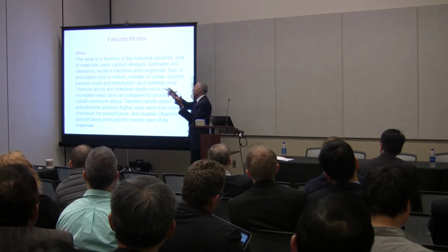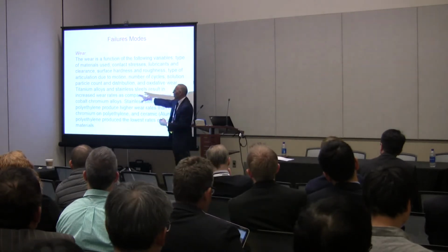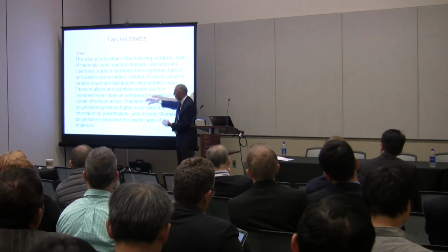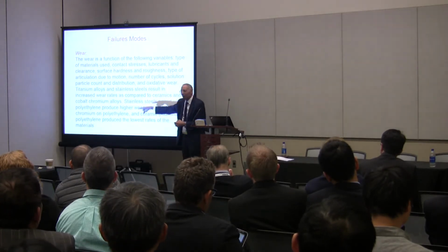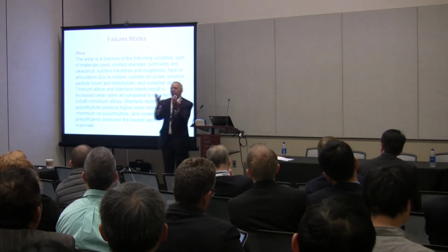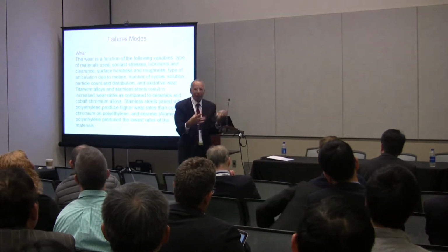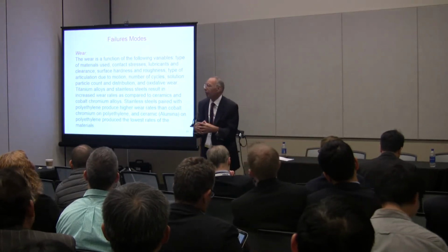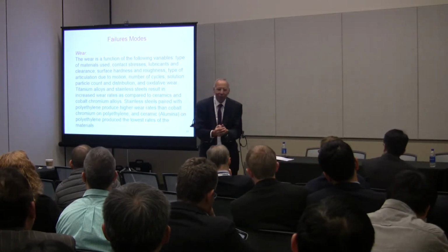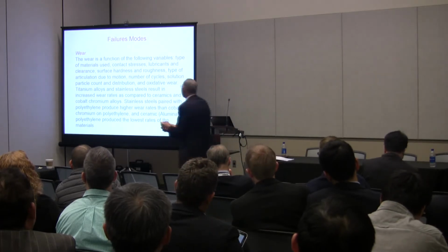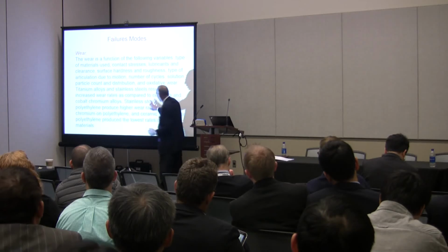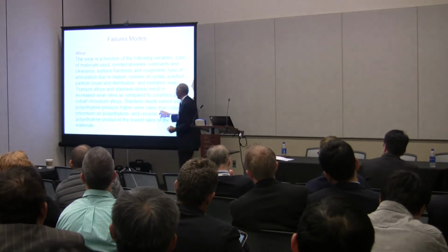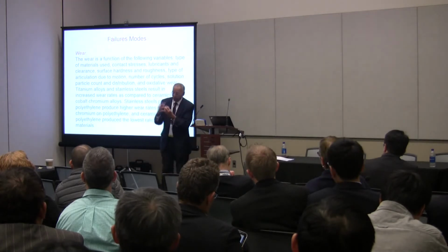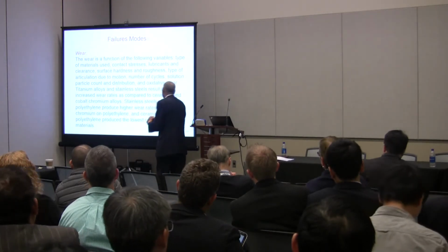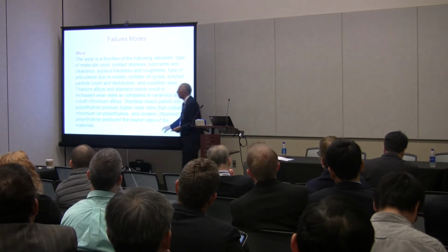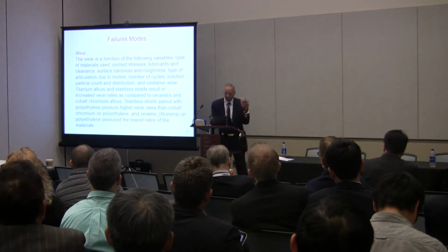And then there is oxidative wear, which is corrosion. It depends on the material you're using. Titanium alloys and stainless steel result in increased wear rates compared to ceramics and cobalt-chromium alloys. Ceramic is actually the most common one, except if you fall, you're going to fracture it. It's a brittle material. So people try to avoid ceramic on ceramic. Stainless steel with polyethylene produces higher wear rates, because steel is a hard material and polyethylene is a softer material, so you have wear. And ceramic on polyethylene produces the lowest rate. So you need to avoid the debris.